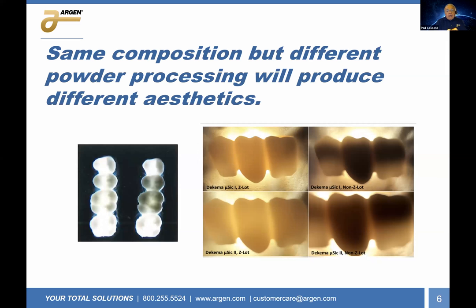Okay. Now, I mentioned before that we took one portion and milled it to a finer grain. These materials now have exactly the same chemistry, but the one on the left-hand side, we'll look at the x-ray first, has dramatically higher translucency than the finer grain one. This is the coarse grain one on the left and the fine grain one on the right. So just by modifying the process, one extra little step to mill it, we've decreased the translucency of the material, and we've negatively impacted the quality.